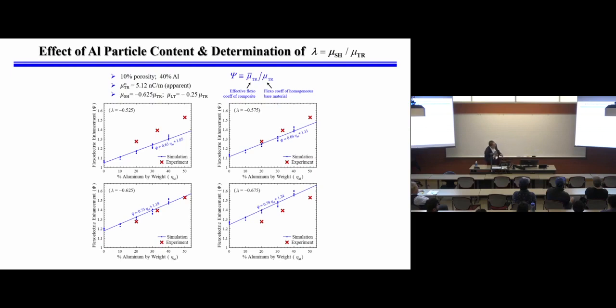Now, here is what computations can do that experiments cannot. How do you figure out the flexoelectric coefficients, the contributions that you cannot measure experimentally? How do you separate them? Experimentally, they can only use different amounts of aluminum and measure the output. And so those are the experimental data points.